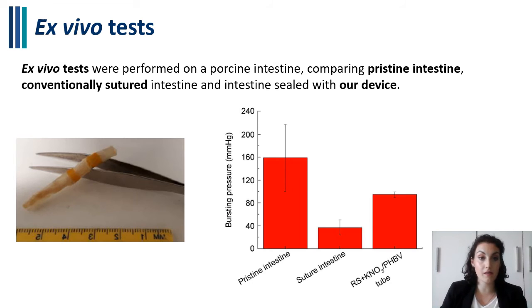Finally, ex vivo tests were performed on a porcine intestine, comparing the burst pressure of a pristine intestine, a conventionally sutured intestine, and an intestine sealed with our device. As you can see from this slide, the burst pressure of an intestine sutured with our device increased if compared with the one of a conventionally sutured intestine, and is comparable with the pristine one.